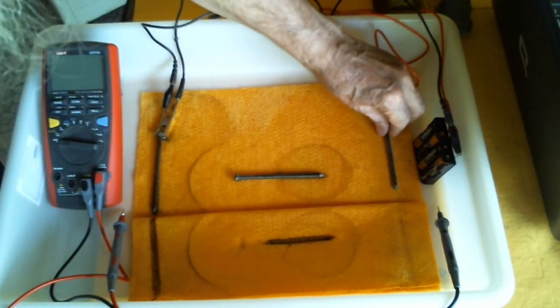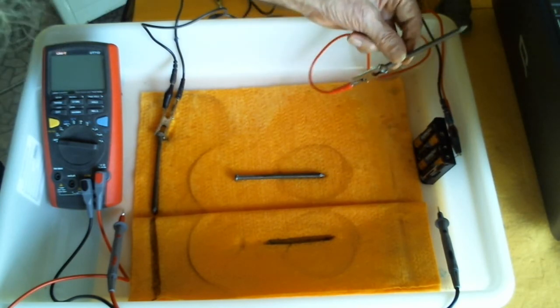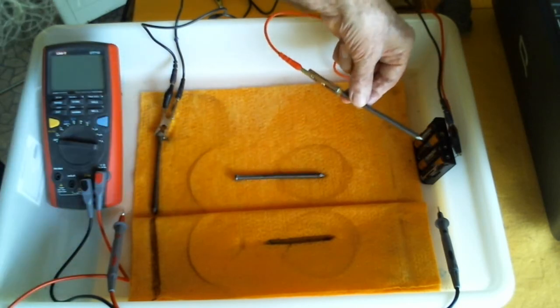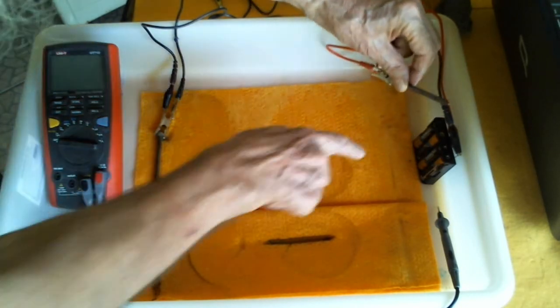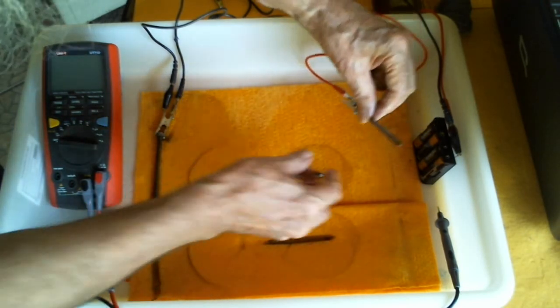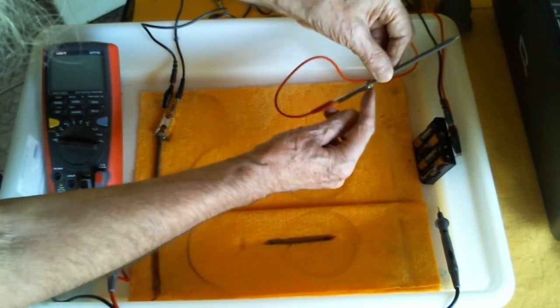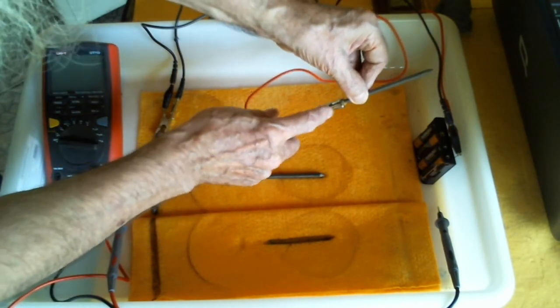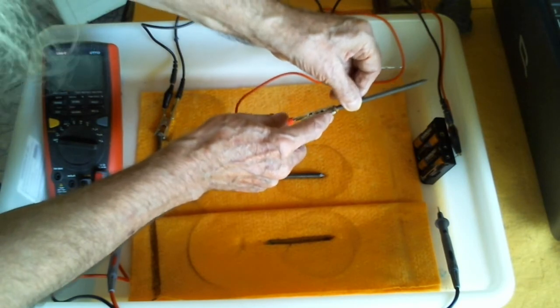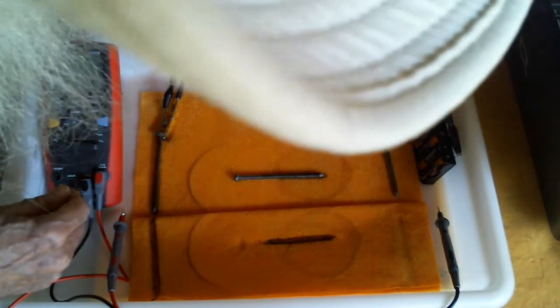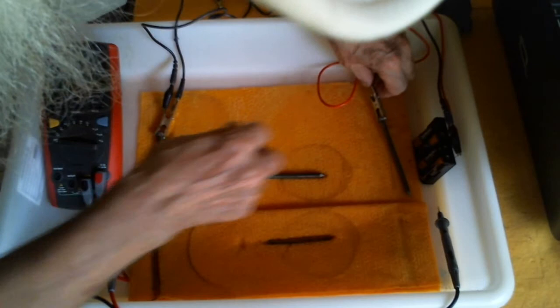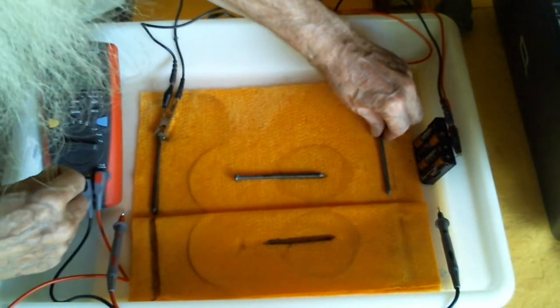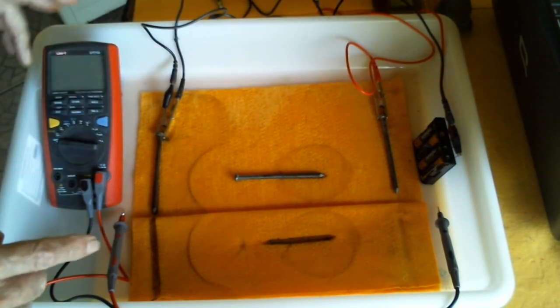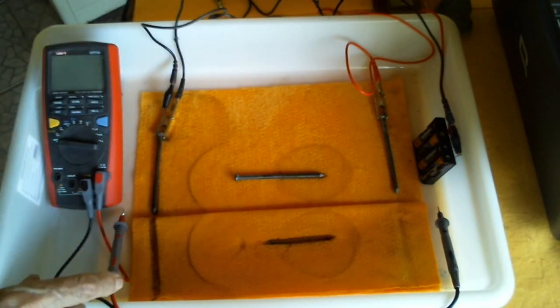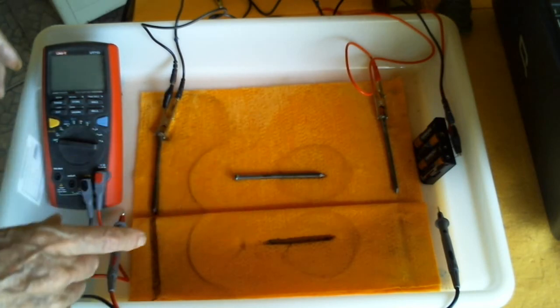This is the protected nail, or the pipe, and you can see no corrosion at all. You can see no corrosion product there or there. You can see a certain amount of corrosion here due to the difference between this nickel-plated crocodile clip and the steel, and that has caused a tiny bit of corrosion at that point. So here we have a perfect demonstration of corrosion itself, how it happens, and the results of that corrosion itself.